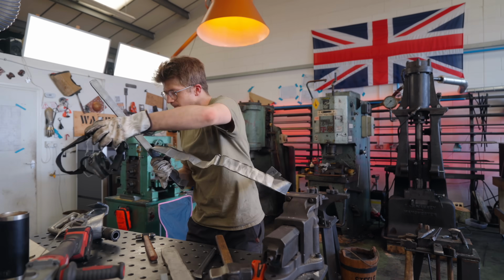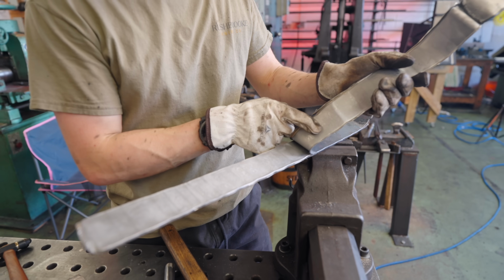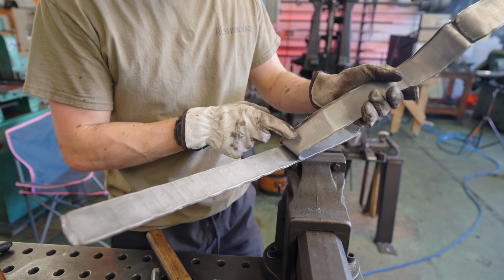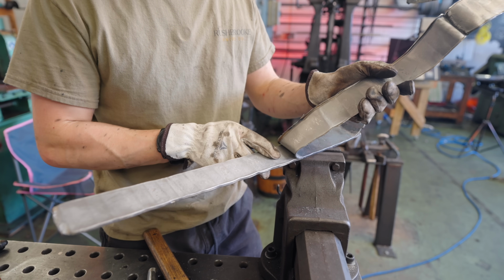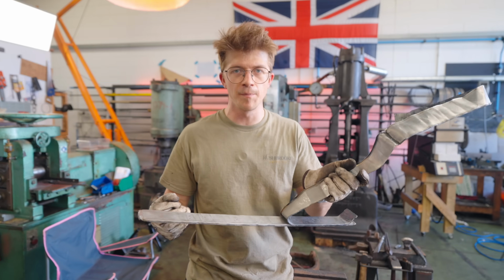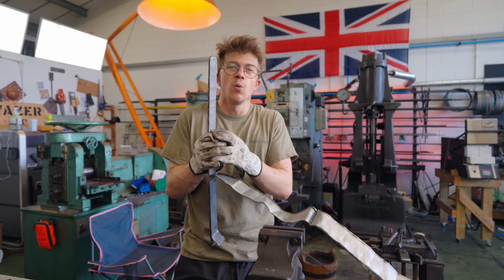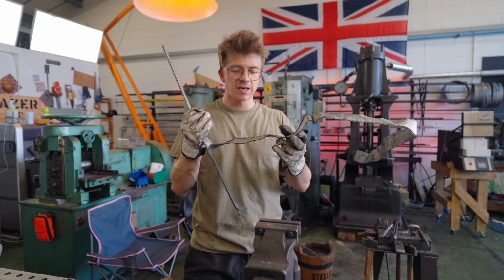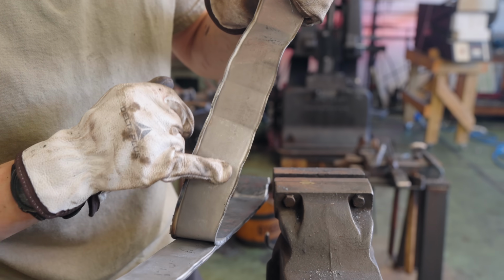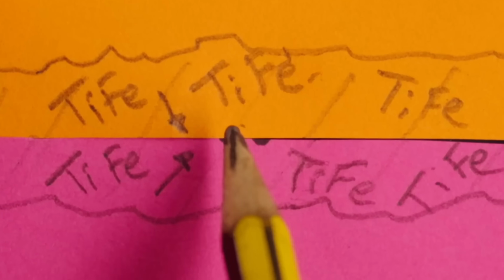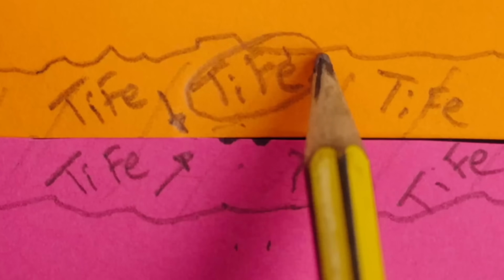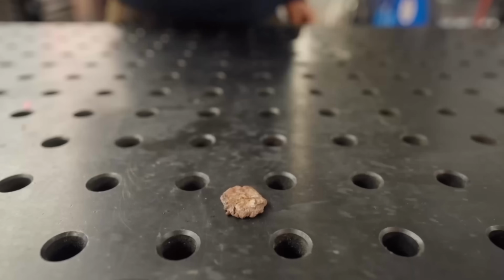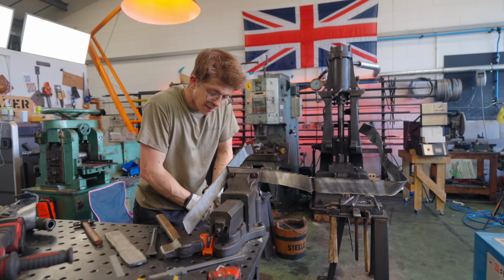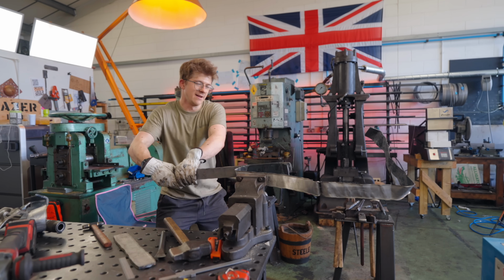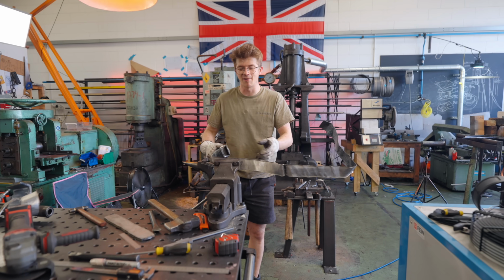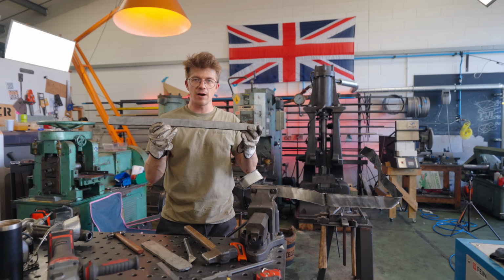See, what's happened here is when we heated up our titanium and we heated up our steel and we smashed them together, the iron atoms and the titanium atoms, they reacted to form what's called an intermetallic compound. So instead of just bonding together, with that temperature, they were able to react and form something completely new. And it's this light gray that you can see on this steel here, and that intermetallic compound of titanium and iron is super, super brittle. It isn't strong enough to be able to hold a katana together, as you can see, because we're ripping it apart right now. That is exactly why we put a layer of nickel in there.